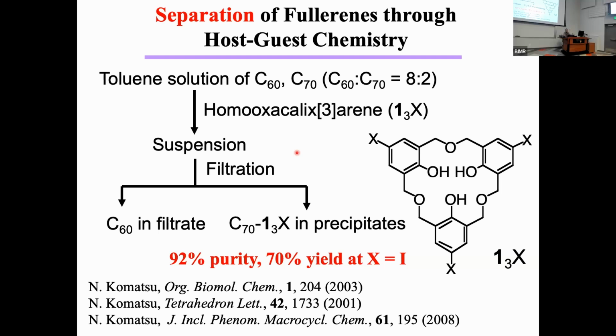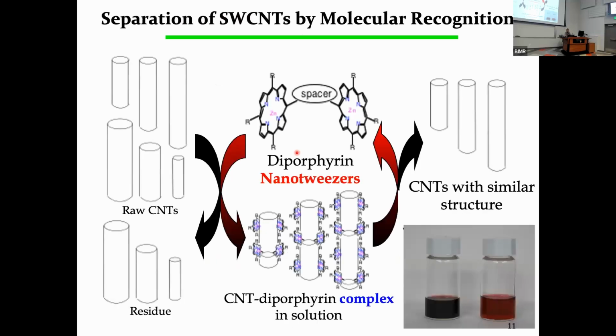We can use the same or a similar strategy to separate the carbon nanotube, but in the very opposite way, because carbon nanotube doesn't dissolve in any kind of solvent. And when it forms a complex, if we can successfully dissolve it in that solvent, of course we can easily separate the precipitate and the solution or the extract. Of course, at that time, if the host molecule recognizes some structure of the carbon nanotube, we can also separate the structure of the carbon nanotube at the same time. So this is our strategy to separate the carbon nanotube, the opposite way to the fullerene case.